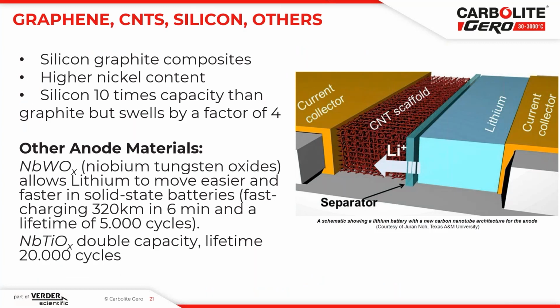Yeah, but not only nickel is very important in batteries, but also the research with respect to graphene, CNTs, which are carbon nanotubes, silicon, and other new materials. And why is that? The silicon graphite composites, they have a higher capacity and a higher density. So if you would use pure silicon, the capacity of the battery would be 10 times higher because of the storage of the lithium. So silicon can store much more lithium. But there is a very critical factor, and this is the swelling. And when silicon starts to swell, it will destroy the battery. It might even explode. So therefore, there are composite materials under research. It is a combination of coated silicon with graphite.